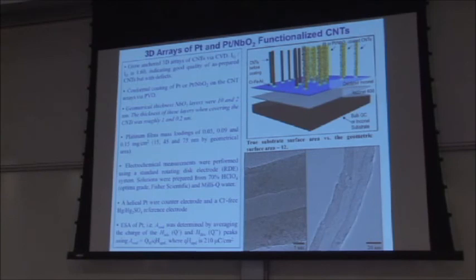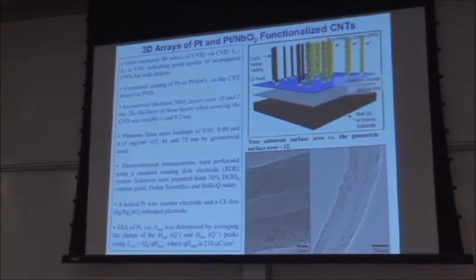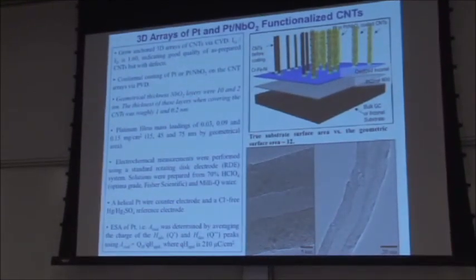In addition to obtaining a remarkable activity enhancement relative to commercial platinum on carbon, the thing that we were really impressed by is that there was, I wouldn't say negligible, but very low reduction in activity even after 30,000 cycles. So if you look at the initial 30,000 cycles, your change in your overpotential is fairly small. So this inspired us. This particular structure, for various reasons, A, it's been done, and B, it wasn't commercializable. We tried something different. So rather than having the niobium oxide, then the platinum, then the carbon, we actually said, why not have the carbon, a very, very thin layer of niobium oxide, really a sub-nanometer layer of niobium oxide, and then the platinum. So a bit of a different geometry.